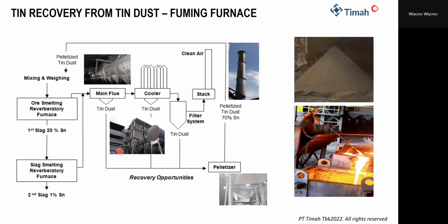And then this is tin recovery from tin dust. Tin dust is obtained from the first stage of tin smelting and the second stage of tin smelting. We collect the tin dust in the main flue and in the off-gas system. The off-gas system consists of the main flue, cooler, and then dust collecting system. We collect the dust, and then for an effective process, we agglomerate the dust into pellets before the dust is resmelted in the furnace.